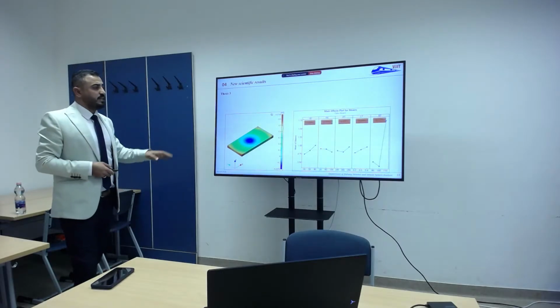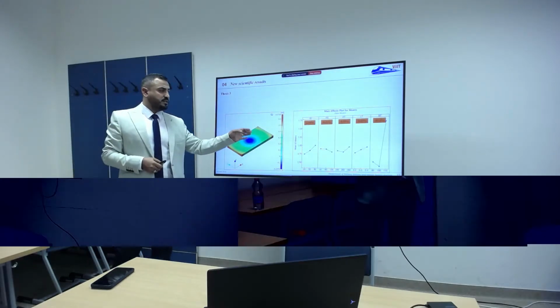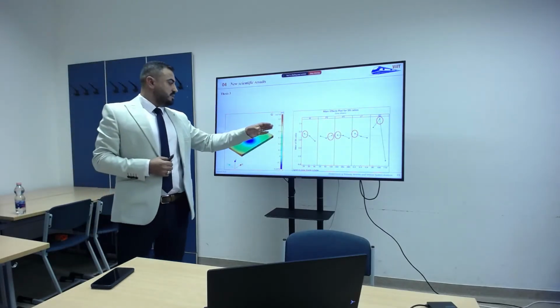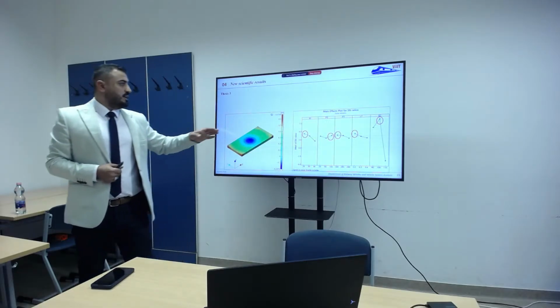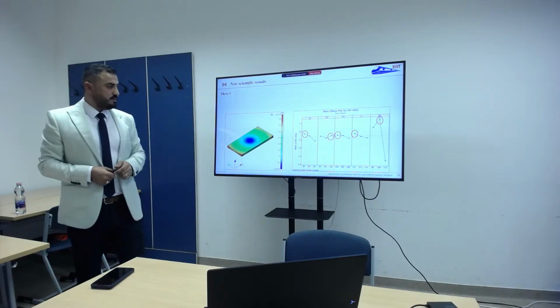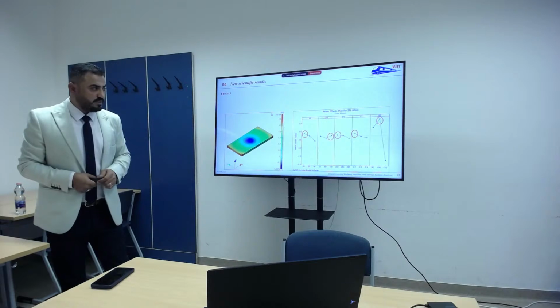I employed the Taguchi orthogonal array for this investigation, and I found that the bed temperature was the most significant factor with about 82% of contribution, while the others were less than 5%. Moreover, the optimal levels for this research were, as we can see here, infill density 20%, printing speed 100 millimeters per second, printing temperature 240 degrees, layer thickness 0.2 millimeter, and bed temperature 100 degrees Celsius.